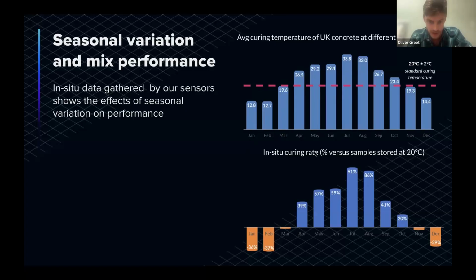In the chart on the bottom right-hand corner, I've run that through the maturity functions I showed you earlier to get an appreciation of the curing rate as a consequence of that thermal environment. So again, this is essentially the relative rate of curing versus a cube stored at 20 degrees Celsius. And you can see here in the middle of summer, the concrete within the element itself can be curing around twice as quickly as the cube might otherwise suggest. And conversely, in winter, it might be curing 30 or so % slower.